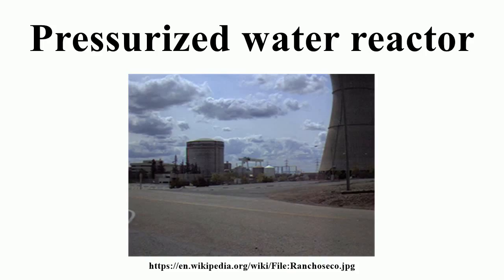Fuel. After enrichment, the uranium dioxide powder is fired in a high-temperature sintering furnace to create hard, ceramic pellets of enriched uranium dioxide. The cylindrical pellets are then clad in a corrosion-resistant zirconium metal alloy, zircaloy, which are backfilled with helium to aid heat conduction and detect leakages. Zircaloy is chosen because of its mechanical properties and its low absorption cross-section.